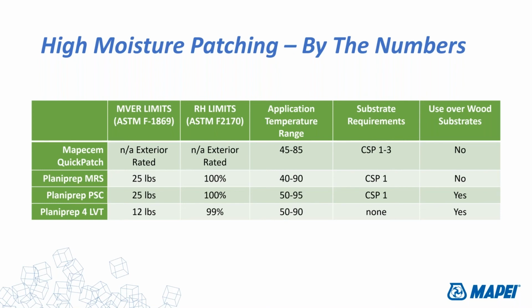Planiprep 4 LVT, a 12 pound 99% solution, 50 to 90. Substrate requirements here are none. You can basically use this on non-porous substrates. We recommend it over waterproofing membranes. We recommend this over existing porcelain tile, over a wide variety of substrates that have no porosity. So again, that's kind of why you have to apply it thin, because it does have to evaporate in order to dry, but it can be used over a lot of different substrates, including wood.